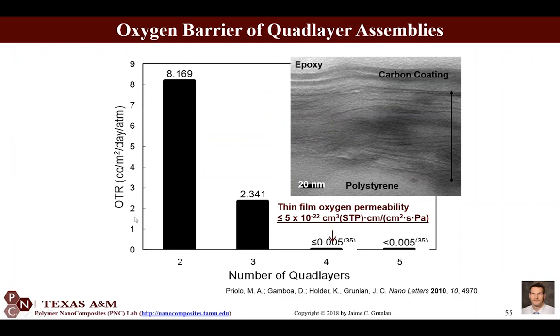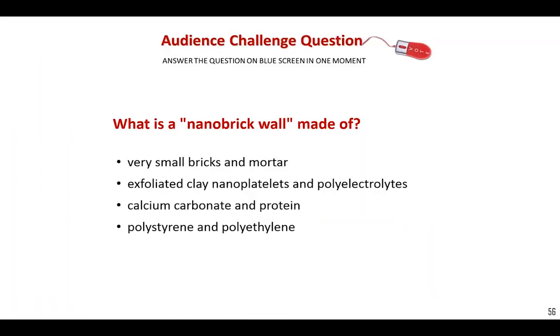And when we look at oxygen transmission rate now, just 4 quad layers gets me what we would call an undetectable oxygen barrier. This is measured by a tool called a MOCON permeation instrument, and it's well known in the food packaging industry. You can also see in this TEM cross section how much more spaced out the clay is relative to that first image I showed you that was just a bilayer with a single polymer layer between each clay layer.